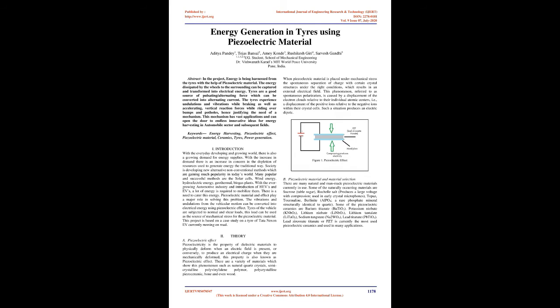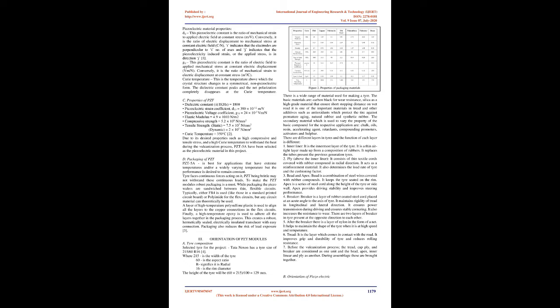Curie temperature. This is the temperature above which the crystal structure changes to a symmetrical, non-piezoelectric form. The dielectric constant peaks and the net polarization completely disappears at the Curie temperature. Properties of PZT. Dielectric constant, at 1 kHz, equals 1800. Piezoelectric strain coefficient, d33 equals 390 times 10^-12 m/V. Piezoelectric voltage coefficient, g33 equals 24 times 10^-3 Vm/N. Elastic modulus equals 4.9 times 10^10 N/m2.